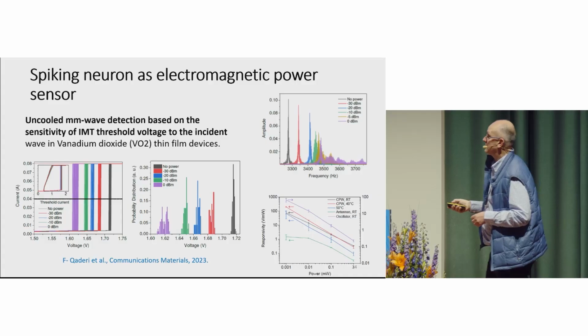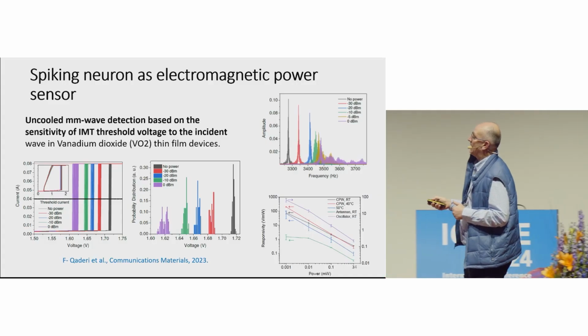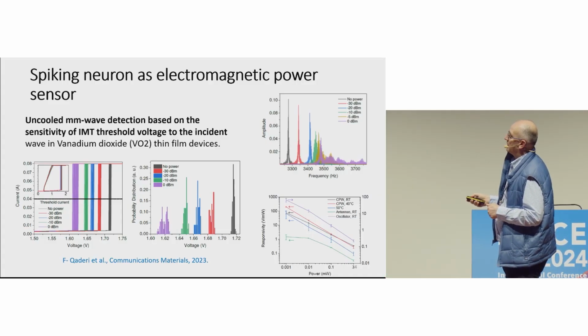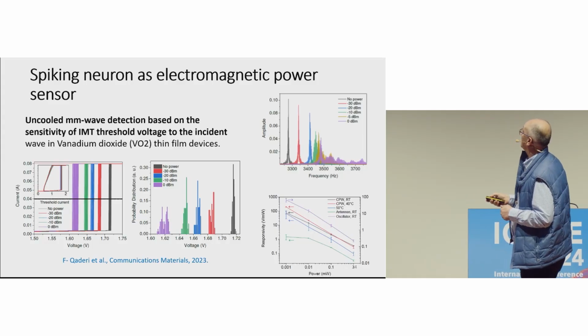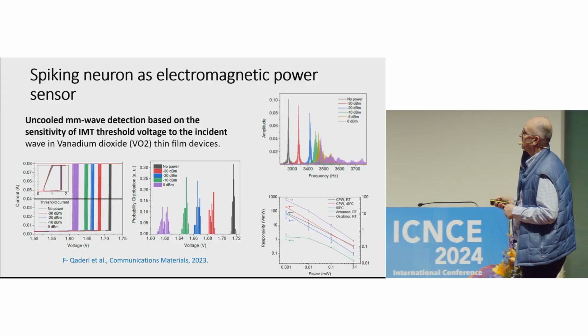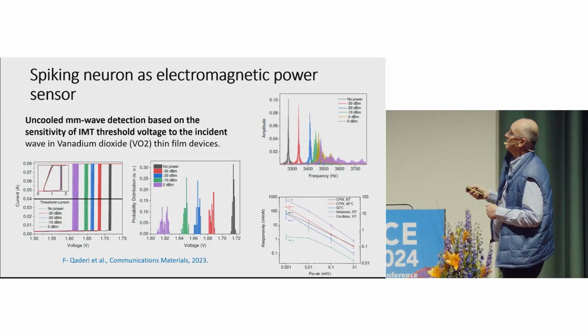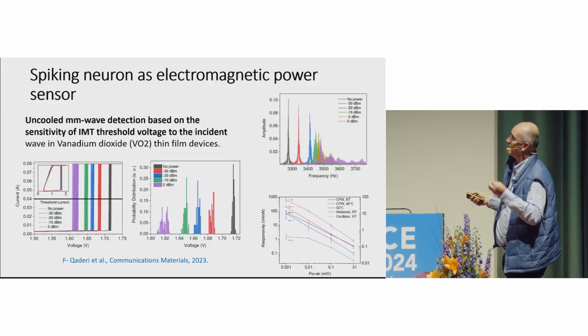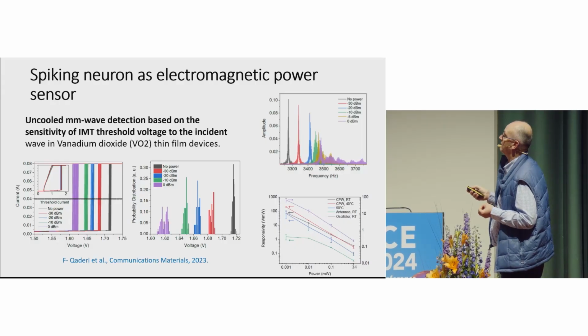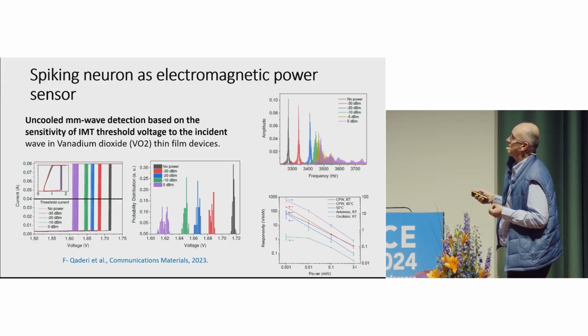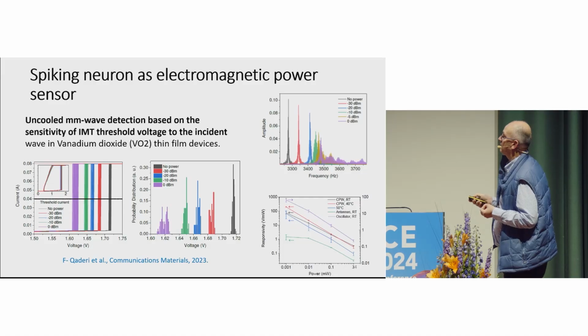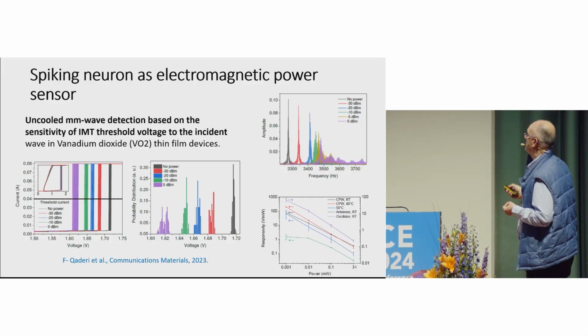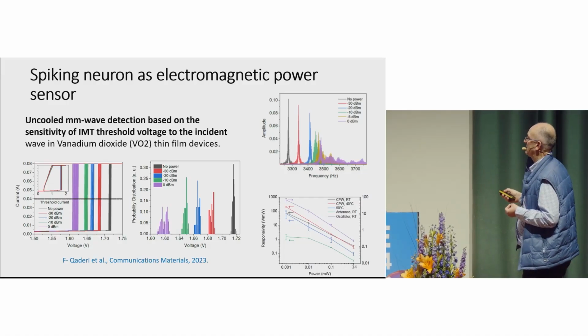And this is a very nice result that I show to you, is that here you are practically changing the switching point according to the power that you apply here. Here is in the gigahertz range. So you are practically building the simplest, smallest, and cheapest uncooled millimeter wave detection based on the sensitivity of the threshold voltage to the incident wave on this device. And these are practically the responsive features that are in this paper, benchmarked according to the literature.